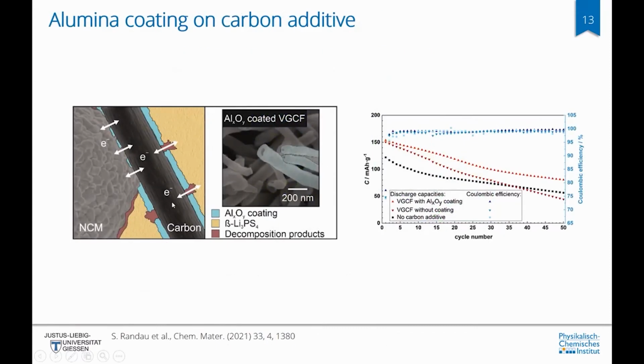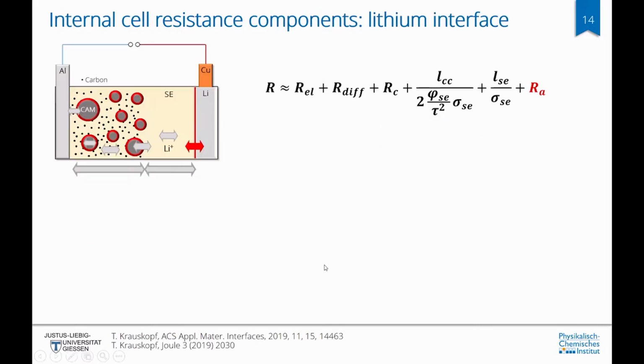Equally, we investigated the carbon degradation, or better, the degradation at the carbon interface, and found a method of coating the carbon with an alumina coating by ALD, and with the lithium thiophosphate Li3PS4 electrolyte, this creates an improved cell performance when using the carbon additive, and the stability during cycling is then further improved with the alumina coating on the carbon itself. So finally, we will now look at the lithium interface with the solid electrolyte.